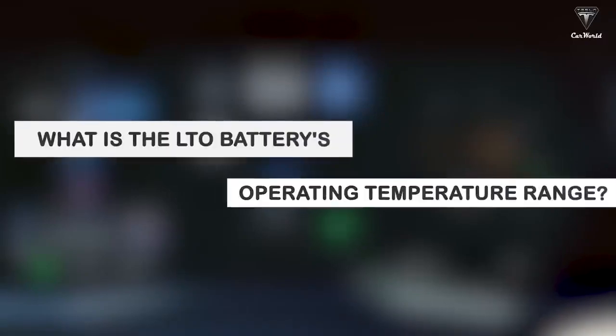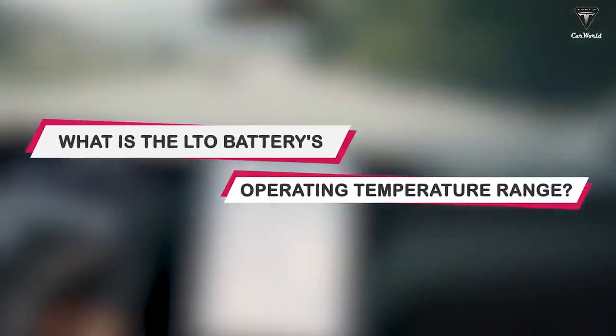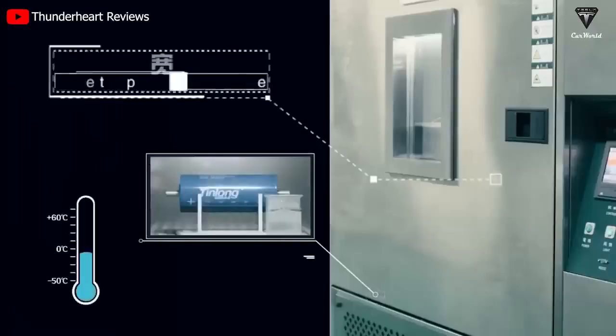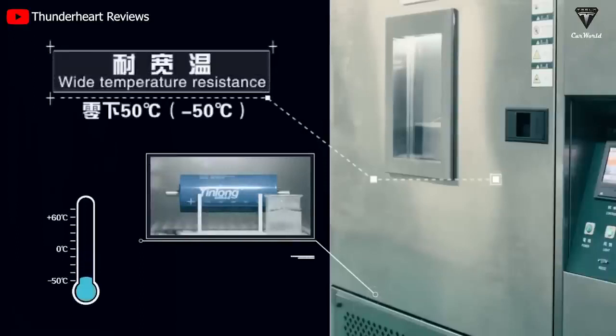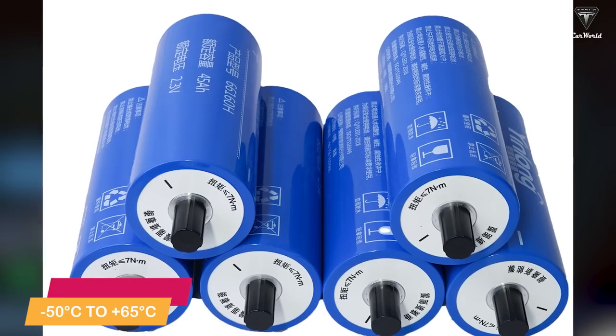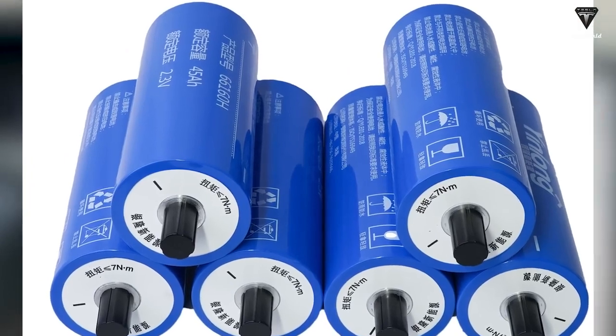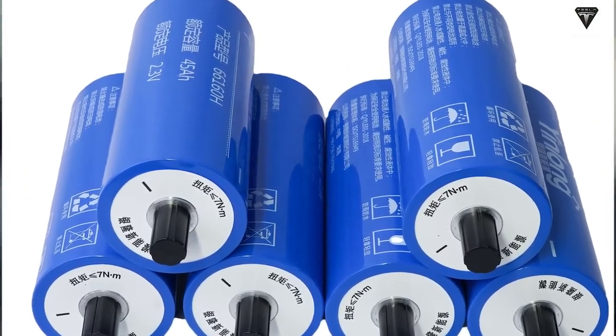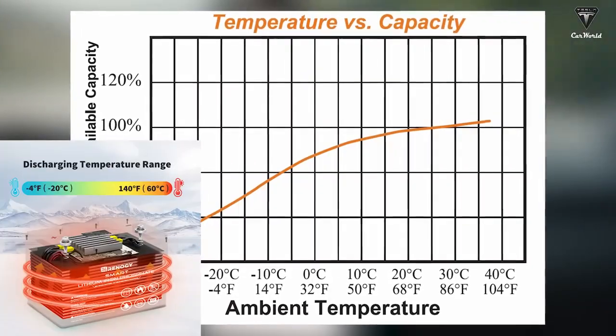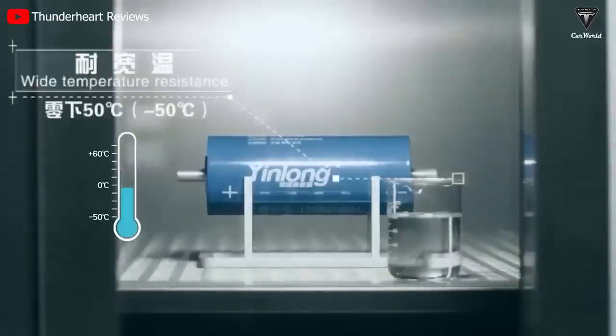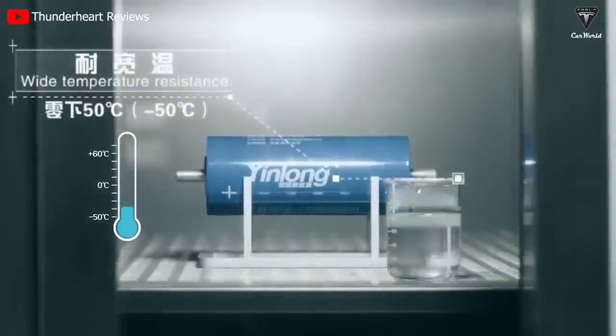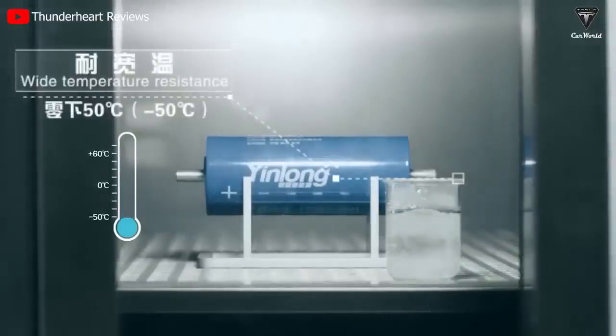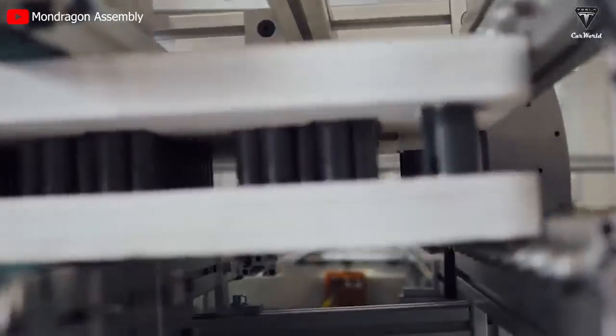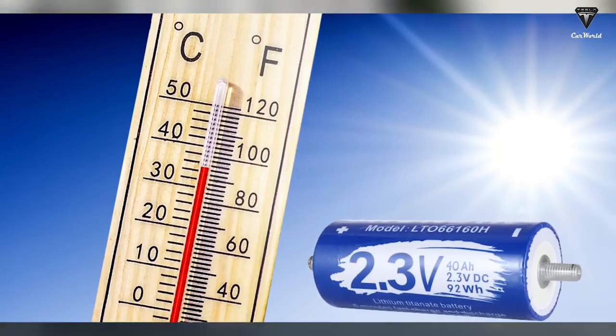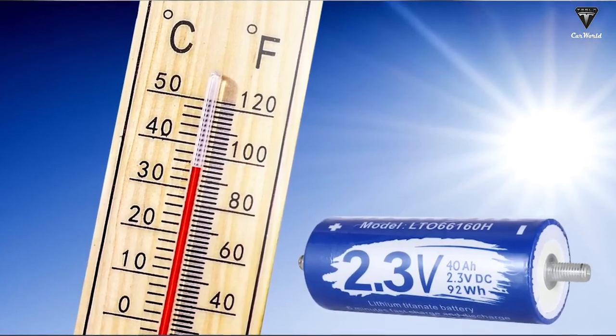So, what is the LTO battery's operating temperature range? It can be used in temperatures ranging as low as negative 50 centigrade up to 65 degrees centigrade with little loss of capacity or performance. While some batteries lose performance in cold conditions, LTO cells continue to operate normally in temps as low as negative 50 centigrade. Special products can work stably at negative 50 centigrade without being affected by the environment and temperature.